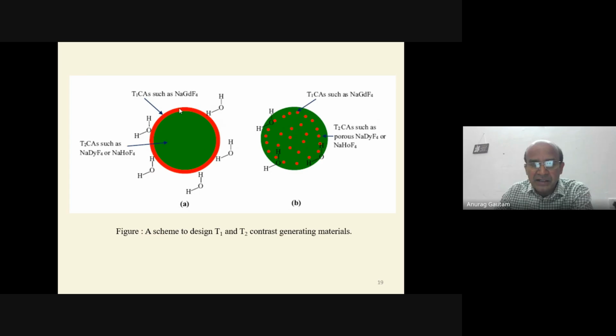In this core-shell structure, these are not porous. But if we can somehow make this green part, which is sodium dysprosium fluoride or sodium holmium fluoride, a porous structure, where the T1 molecules are inside those pores and water is still able to access those pores. If they are unable to access, then T1 will not work. So this is a kind of porous structure where we keep the shell material within those pores, and the water molecule can reach there. If they reach there, we will still see a T1 based contrast agent, and T2 depends on overall magnetization. So T2 has no problem. The higher the overall magnetization, the better the T2 contrast.